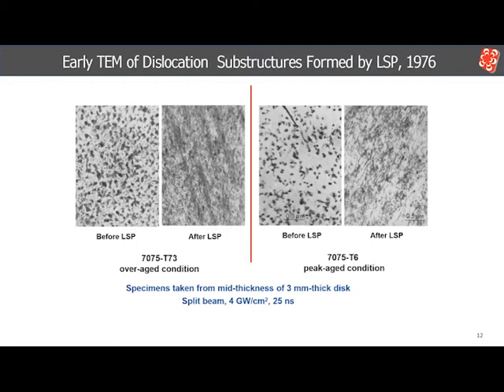strength. Because these very fine precipitates are so small and finely distributed, the shock-driven dislocations must cut through them. The high yield stress reflects the stress needed to push the dislocations through the precipitates, but above this stress they can move with little further resistance. Thus, fewer dislocations are formed, and the strength is actually decreased by the shock wave because it leaves behind some mobile dislocations and glide paths for movement during the subsequent tensile test.